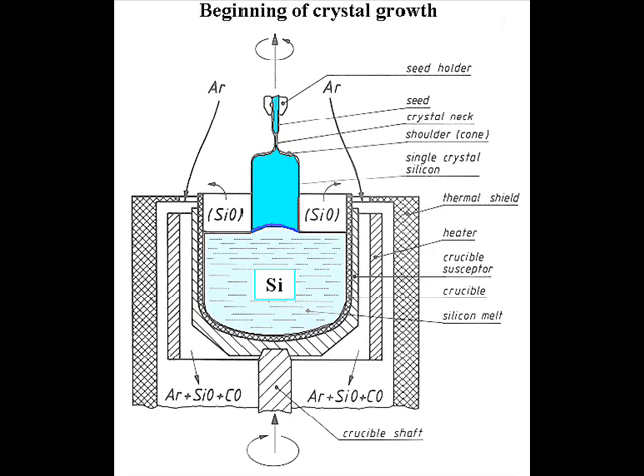The seed crystal is inserted into the liquid silicon and at the predetermined temperature, the seed crystal is withdrawn. For homogeneity purposes, both the crucible and the seed crystal are rotated in opposite directions. The speed and development during growth differs from one fabricator to another, making it very valuable information.